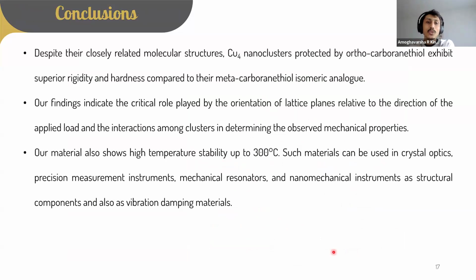Now, coming to the conclusion of my work: despite their closely related molecular structures, copper 4 nanoclusters protected by orthocarboranethiol exhibit superior rigidity and hardness compared to their metacarboranethiol isomeric analog. Our findings indicate the critical role played by the orientation of lattice planes relative to the direction of the applied load and the interactions among clusters in determining the observed mechanical properties.